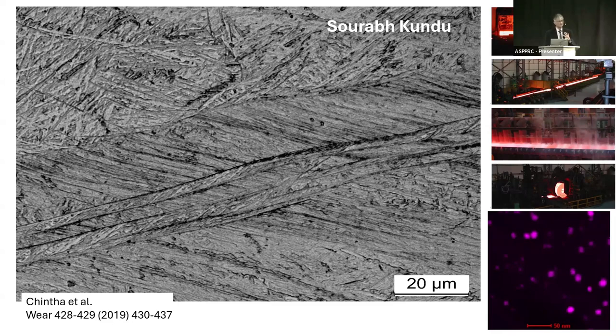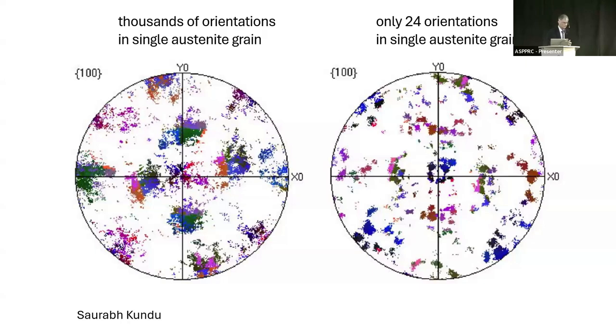And what I want to show you is a different way of looking at this. So these are pole figures. And if you came to the lectures in the morning, then we talked about the orientation relationships like Nishiyama, Wasserman, and so forth. So in a single grain of austenite, you can only get 24 different orientations of plates of martensite. But if I look at this pole figure on this side, I have thousands of orientations in a single austenite grain. And that's very good because if you're looking at cleavage crack propagation, you want to deflect the crack frequently because that is doing work in creating fracture.